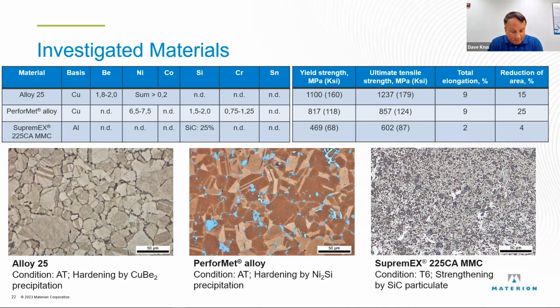But in doing so, you've got that distribution of all those beryllides that kind of mucks up the matrix, and it doesn't conduct heat or electricity, but mainly heat for our purposes, as well as the Performat alloy. Performat has very hard nickel silicides in a copper alloy matrix, but you see there's conduction paths in between. And going to the Supreme, that's Performat Supremex, those are 0.3 micron average size particles, making it easier to machine than, for example, cast MMCs. But that has a higher thermal conductivity than aluminum itself slightly, because silicon carbide conducts heat better than aluminum.